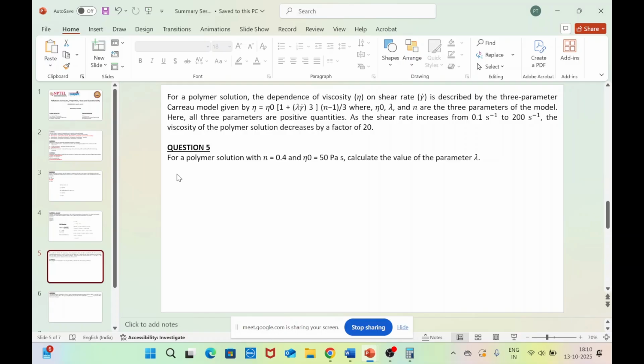So based on that three parameter model, here is described as eta equal to eta naught times 1 plus lambda gamma dot whole cube, the entire whole power n minus 1 by 3, where eta naught, lambda and n are the three parameters of the model. All the three parameters are positive quantity.